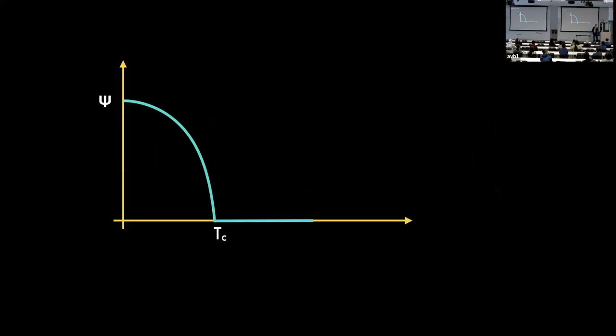Okay, so what happens as a function of temperature to this order parameter? I've got an order parameter on the y-axis here, let's call it psi. It's just some way to characterize how well ordered these systems are. At high temperature, I want this order parameter to be 0. In other words, the system hasn't broken the symmetry, it hasn't ordered. And then at low temperature, I want it to have some transition, which we will call Tc, and then this order parameter will start to grow. That'll be a measure of that broken symmetry coming in, of those interactions becoming relevant. Now, when you see this in the material, this Tc is a measure of the energy scale of those interactions. When your interactions are strong, you can imagine that you start to see this broken symmetry or this ordered state at a very high temperature.